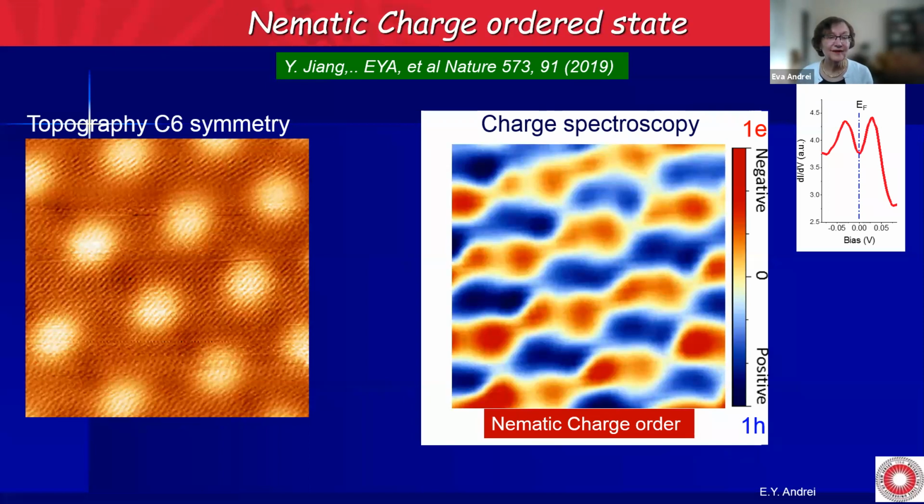When we go to different parts, it's not always in the same direction we see. So it doesn't stay in the same direction. It is kind of a longer crystallographic direction, but it can change direction if you go far away, but it's always there. And when we are away from the magic angle, we don't see this. And when we apply magnetic field, the thing goes away above 10 Tesla. So it looks like it's something intrinsic.